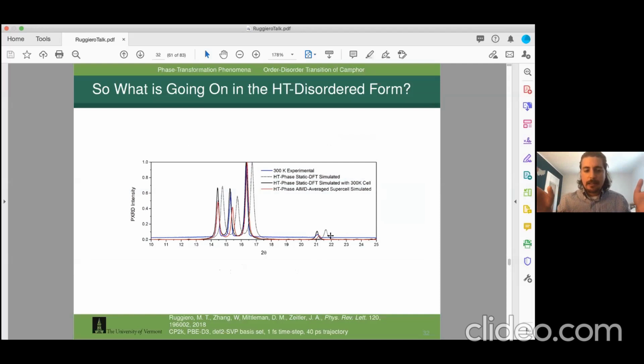I can do a little better if I take the DFT optimization and constrain the unit cell to a higher temperature volume, and then do the optimization again. That gives the black line, which is almost a perfect agreement with the blue line, the experiment.